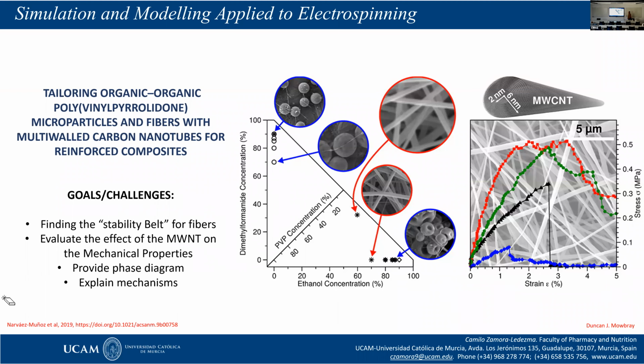We did the same in another work we published in 2019. This time, we were looking at the fabrication of particles and fibers using multi-wall carbon nanotube reinforced composites. We were trying to produce this nice phase diagram in order to find the stability belt in which you can choose the solvent and the PVP concentration if you are looking for only beads, only microspheres, or fibers, or beaded fibers, okay? We also studied the effect of multi-wall carbon nanotubes on the mechanical properties,